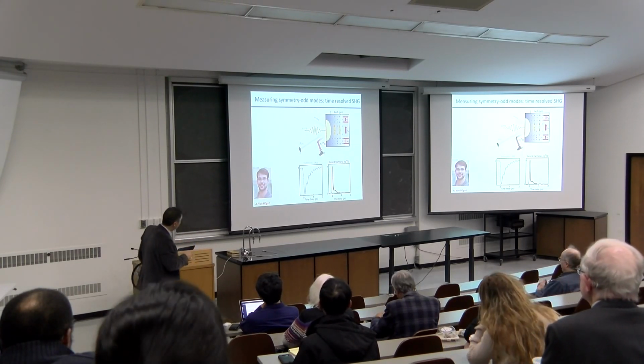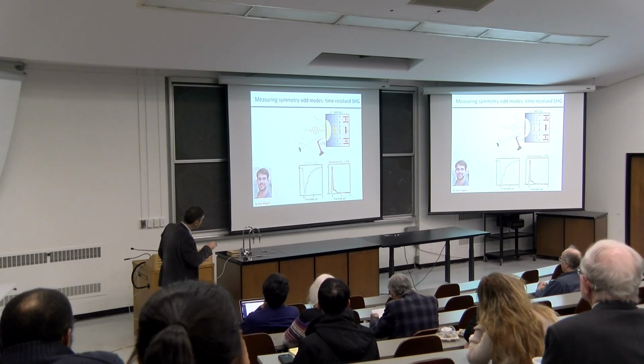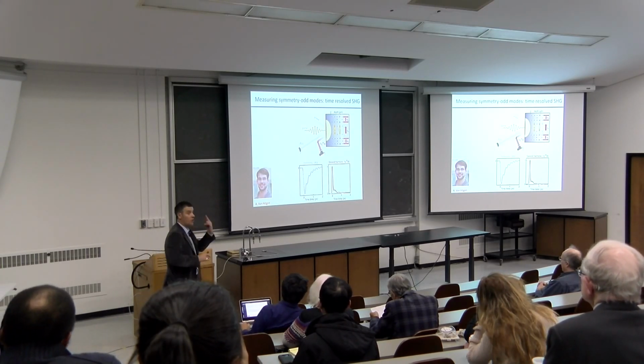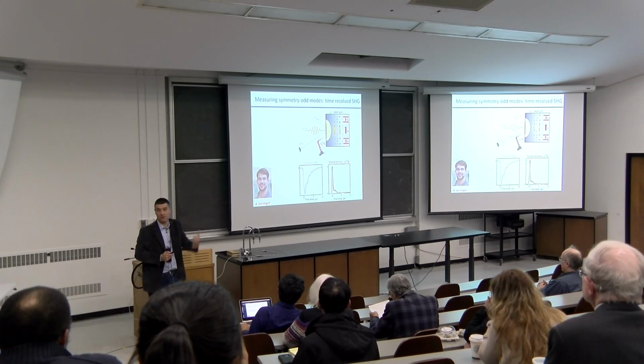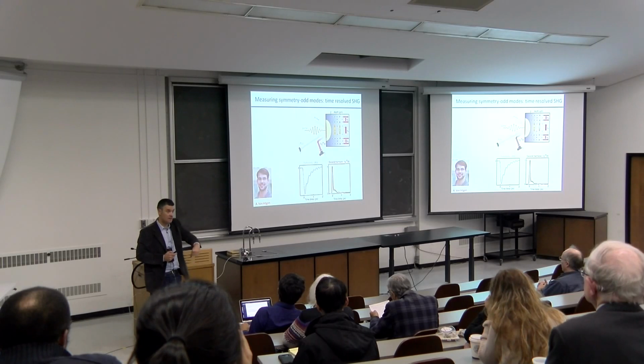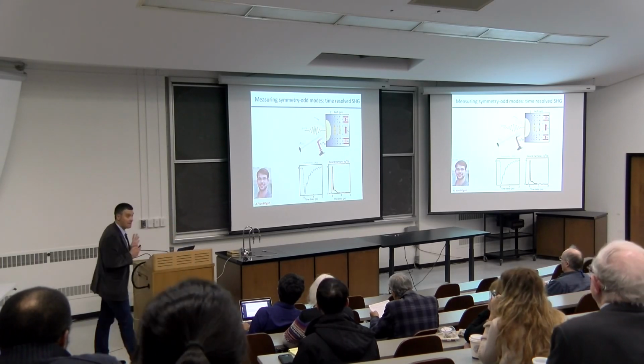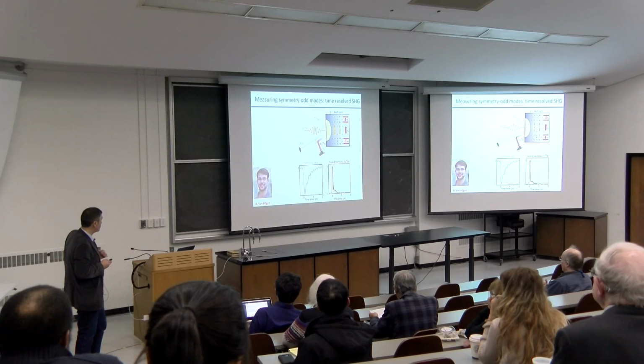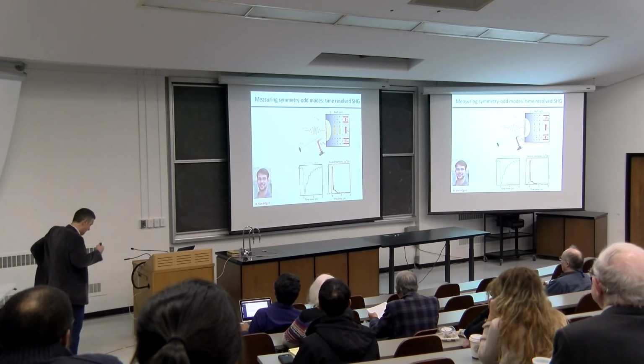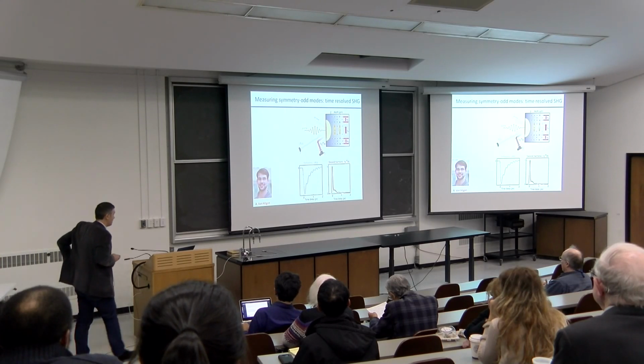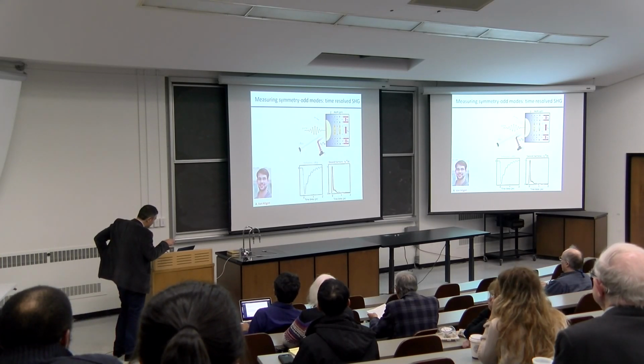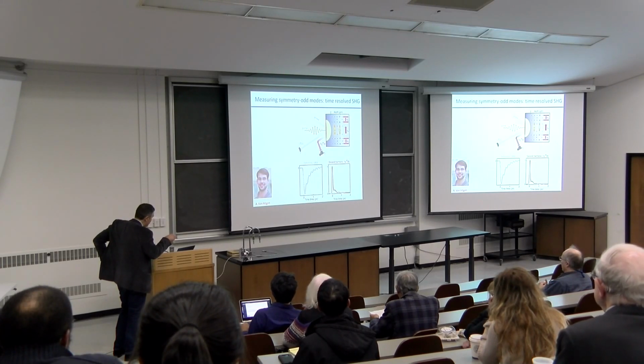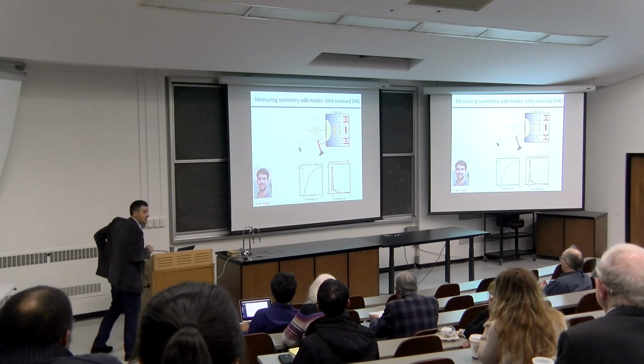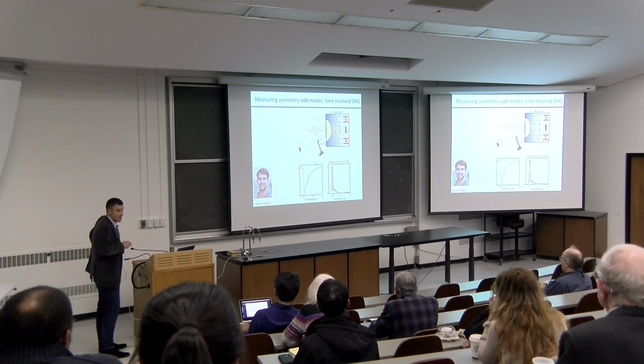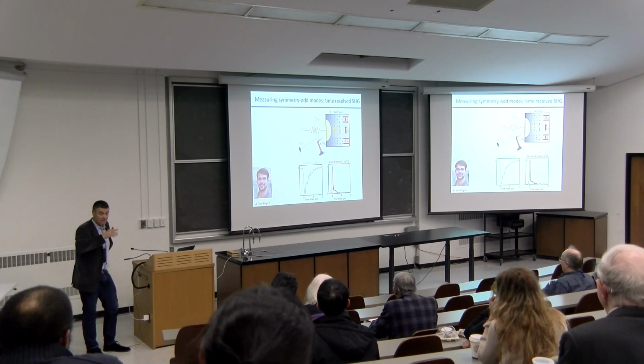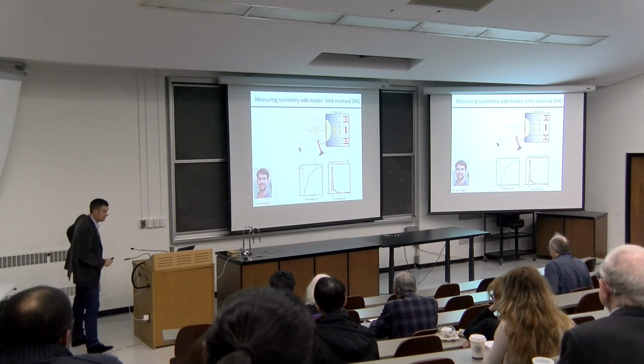So the bottom line is that by measuring the second harmonic as a function of time, I can measure all the odd modes, but also the supercurrents. As these supercurrents go backwards and forwards coherently, they will break inversion, and they will putatively become measurable if the modulation of the second order nonlinearity is large enough. So Alex set out to do these measurements, and sure enough, you can see in the pump probe experiment, you pump the phonon, and then you look at these ringing. This is basically the same experiment that we did before by measuring the terahertz reflection, but now we're measuring the coherencies in the second harmonic as a function of time.